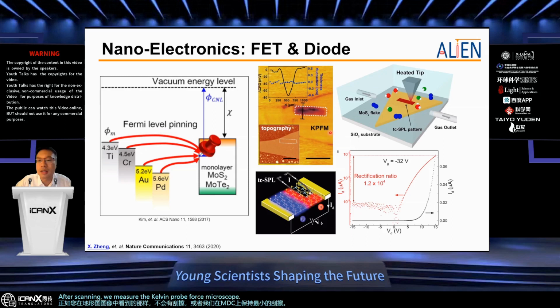After scanning, we measure with Kelvin probe force microscopy. This is another scanning probe based microscope, which measures the Fermi level of the sample, representing the carrier concentration in the sample. As you can see, after the thermal scanning of the TMDC flake, the carrier concentration has been modified. So this is another way to show the manipulation of carrier concentration, which in turn tunes the electrical properties in the TMDC. By tuning the gas environment, we could tune the sample to an N-type semiconductor or to a P-type semiconductor, simply depending on the gas flow.